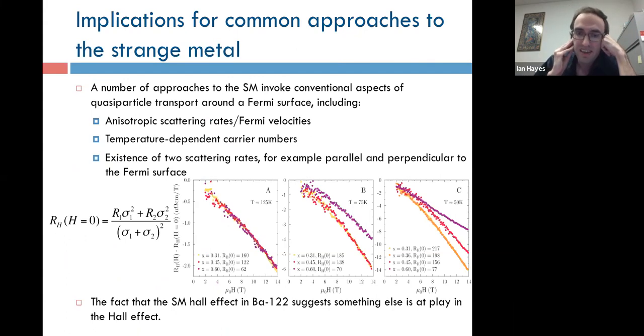The second comment I want to make is that it's rather striking that this strange metal field dependence seems to come in as an additive term. In other words, the absolute value of the change in RH is the same as a function of field at high temperature across a range of doping, despite the fact that the zero field RH is changing quite a bit. And so if we think that this effect is coming from some change in mobilities or carrier densities, even something generated by an unusual anisotropic scattering rate or antiferromagnetic fluctuation, you still think that the effect would then be filtered through this multiband formula and the competition between the Hall coefficients on these 4 different Fermi surface sheets, which are all changing across the phase diagram.